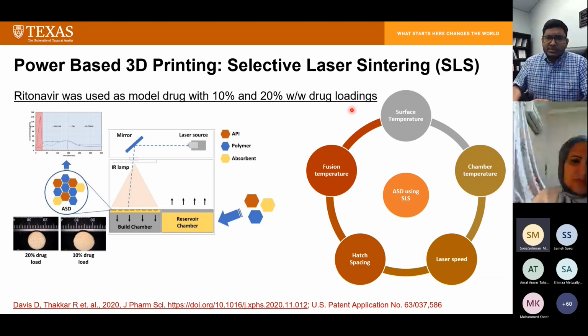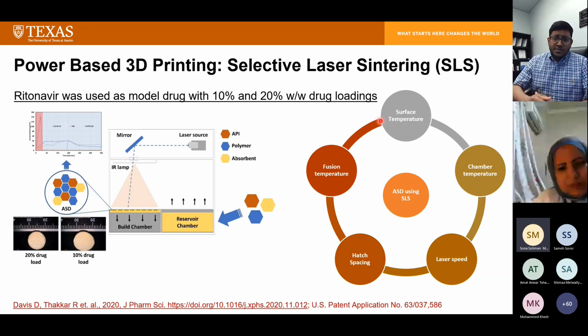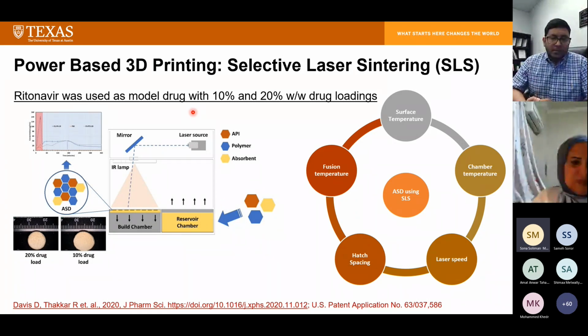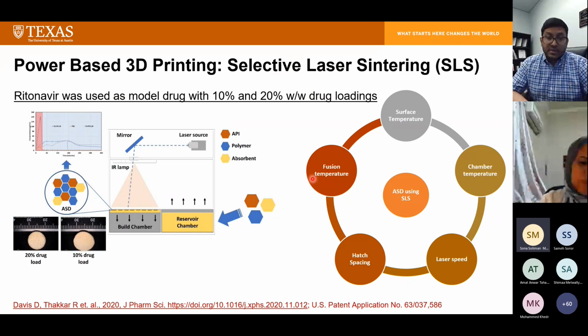So one example is the selective laser sintering based printing option. Here in this first case study, we used ritonavir, which is an antiviral drug for HIV, and we used 10% and 20% loadings. And ritonavir is a highly unstable and heat sensitive drug. It has very poor solubility. So we used actually our selective laser sintering based concept for the single step production of amorphous tablet without jeopardizing or compromising the stability of that drug.